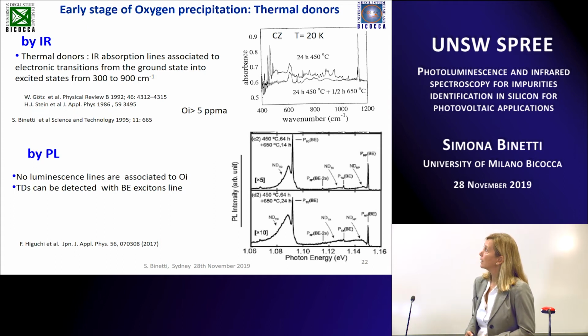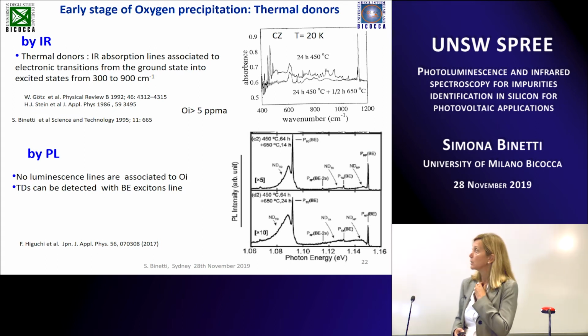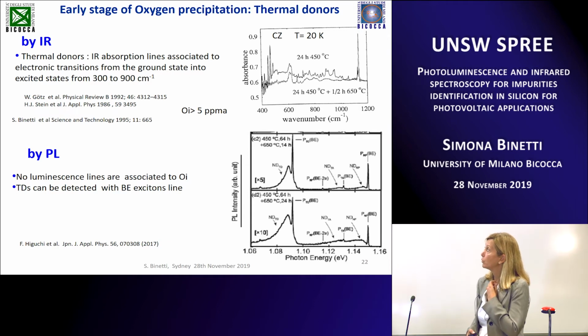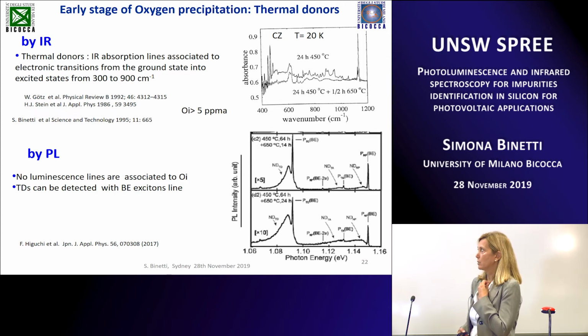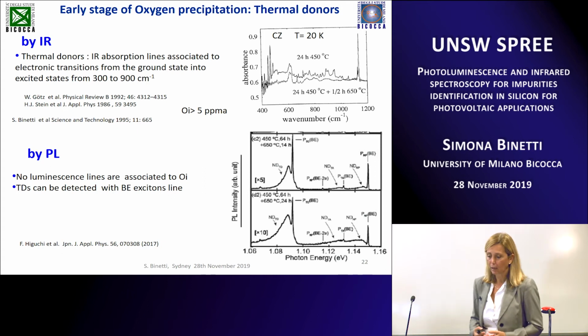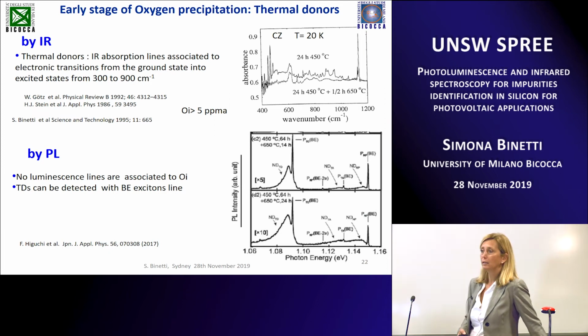You can see the lines in the region between 600 and 1000 cm^-1, and so you can detect the presence, and eventually quantify the concentration of donors, or make a comparison with the concentration of donors calculated by resistivity measurement. Also, by photoluminescence, it's possible to have some information about oxygen. No luminescence lines are associated with the oxygen interstitial position, because fortunately the oxygen interstitial does not introduce a level in the band gap, but you can detect thermal donors by the bound exciton lines, like we have seen for any other type of donors and acceptors in your material.